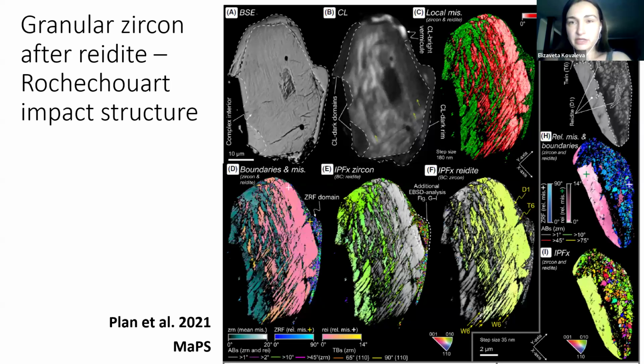And here you can actually see the whole sequence. If you look at panel C, zircon is green and reidite is red. So it was a single grain of zircon. It was partially transformed to reidite due to shock. And then on the far right side of it, that little granular rim, reidite started to revert back to zircon, but instead of a single crystal, it's now composed of very fine granules, and that fragment enlarged is represented in the far right column, G, H, and I. And you can see again relics of this pink reidite inside of this granular zircon mass. So it is not unique to Rochechouart, it's also known from other impact structures. Interpretations were more or less the same as ours.